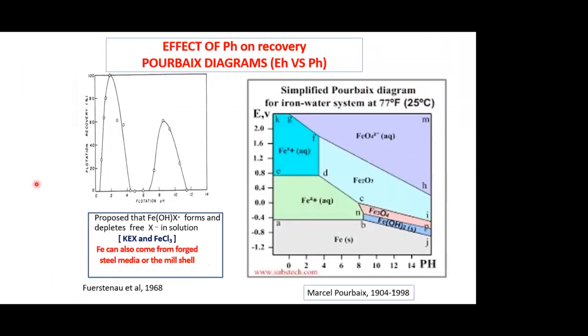This is quite an important diagram because it starts telling us about the whole role of pH in flotation. And here we have a diagram showing the flotation recovery of pyrite as a function of pH. And here we see this interesting phenomenon that round about a pH of 5 to 7, we get zero recovery. And so the question is, what was happening at this point? And it was proposed that you were getting a hydroxy species, and this has now become a popular explanation for these sorts of phenomena, a hydroxy species complexing the xanthate ions out of the solution, depleting the free xanthate ions, and thus inhibiting further flotation.